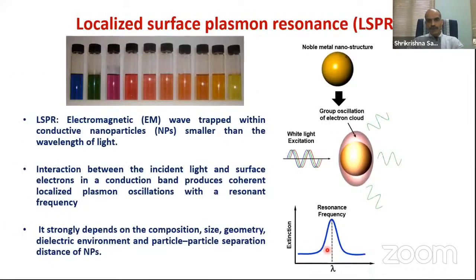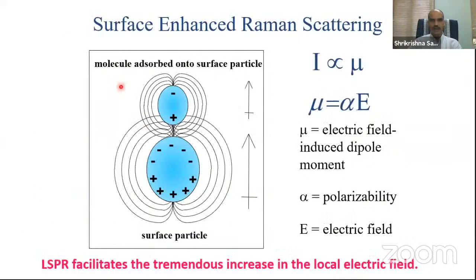So we are aware that the major factor deciding this in surface enhanced Raman spectroscopy is localized surface plasmon resonance. All of you are aware of that. As I already mentioned, when white light having different frequencies is incident on these metal nanoparticles, the plasmon oscillates with a certain frequency, and you get a very high intensity at a certain wavelength. If the incident laser has the same wavelength, there will be enhancement in the signal. This LSPR phenomenon is used to synthesize silver or gold nanoparticles of different colors by changing the size and shape of the nanoparticle.